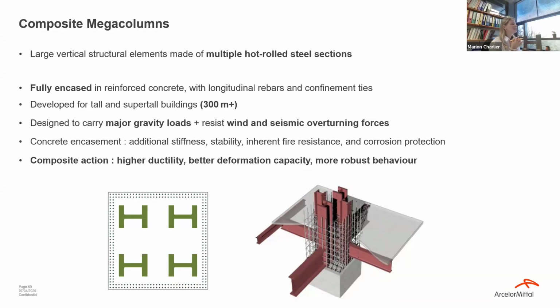Thanks to the concrete around the sections, we have additional stiffness, inherent fire resistance, and corrosion protection for the high-strength steel, but it's really thanks to the composite action that we get a higher ductility, better deformation capacity, and a more robust behavior for these critical vertical elements. Next slide, please.